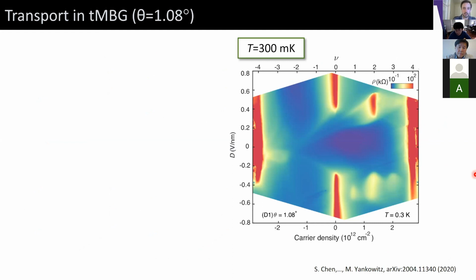And so what we're going to do is measure a sample with a twist angle of about 1.08 degrees at 300 millikelvin. And I'm going to show you a similar thing to what I showed you for the twisted double bilayer. Resistivity as a function of carrier density and electric field. So a lot of the salient features of twisted double bilayer graphene are reproduced here. We have these tunable gaps at the neutrality point. We have gaps at full filling. But now what is distinctly different is that I have to show you both sides of the displacement field, and they're not symmetric. Whereas in twisted double bilayer graphene, they were to within our experimental resolution.